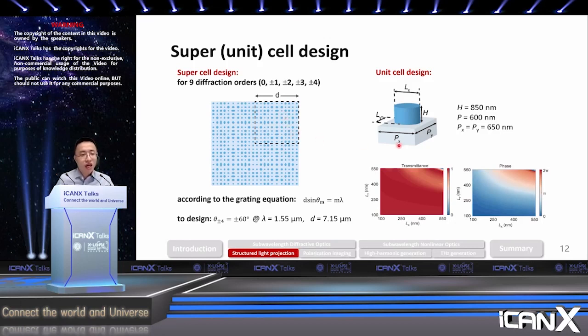To do that, we design this metasurface unit cell, which is composed of this silicon ellipsoid structure. By sweeping the long and short axis of this silicon resonator, you'll see that we can cover the entire 0 to 2 pi phase range while maintaining quite high transmittance. With that, we can get very flexible control in the design of the phase profile.